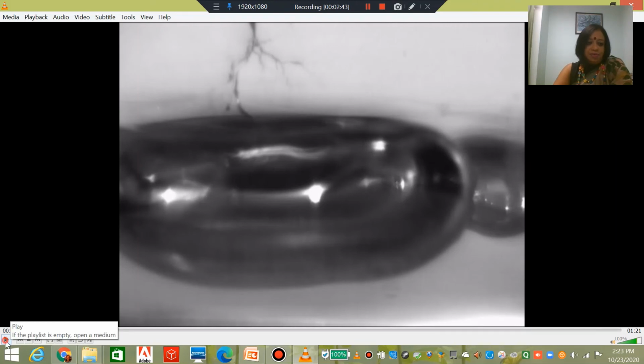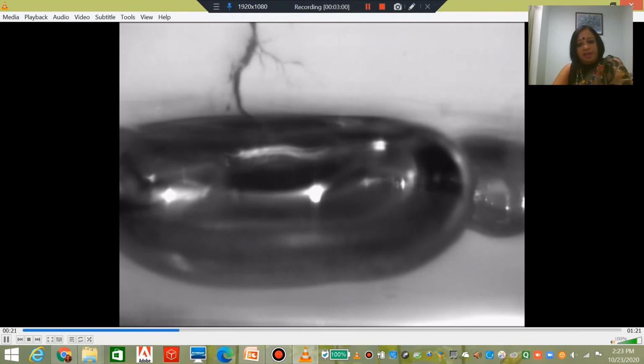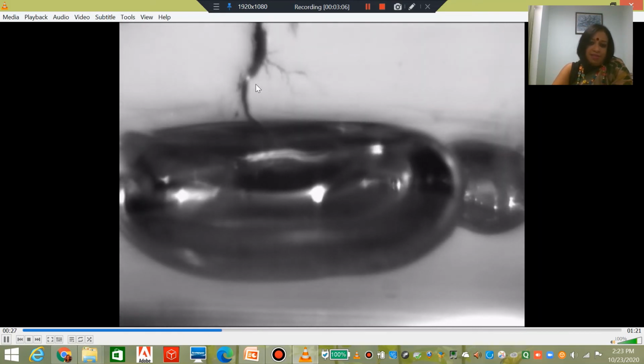When I start the video, you can see that the discharge is traveling upwards. From the void, it is traveling upwards, so charge is flowing upwards, and wherever discharge takes place, after the discharge is extinguished, the channel becomes thicker. So the channel becomes thicker and it can no longer support the discharge, and then the discharge moves to a region where there is still a constriction. So it is as if somebody is digging a path from the needle electrode to the void, and this is happening through PD activity. See, huge PD activity taking place in a particular region.